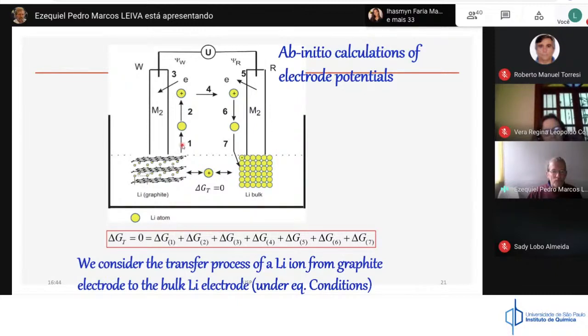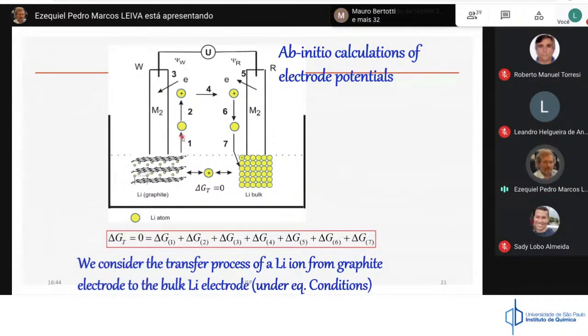You can, for instance, take an atom out of the electrode. To move it further, you can take an electron away from this atom and put it in the same electrode. You can bring later these ions in front of the other electrode. You can put it the same. Finally, at the end of this cycle, you are actually making the transfer of an ion from here to here. That is, the free energy change, which is zero, must be equal to the addition of all the other steps. 1, 2, 3, 4, 5, 6, 7.